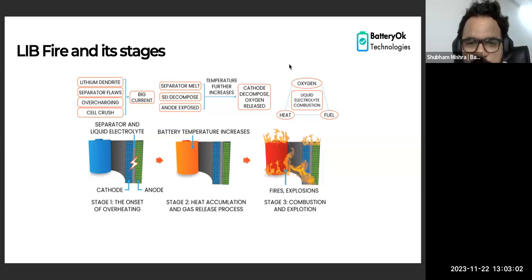Due to this, there will be SEI decomposition, as I have already said. More current will lead to more temperature, following the heat equation I squared R T. It will increase in an almost exponential manner. As we go further, the cathode will decompose, which will lead to more oxygen release, and that will create a chain reaction of fire and flames everywhere.